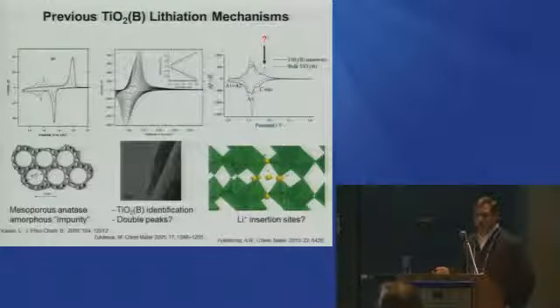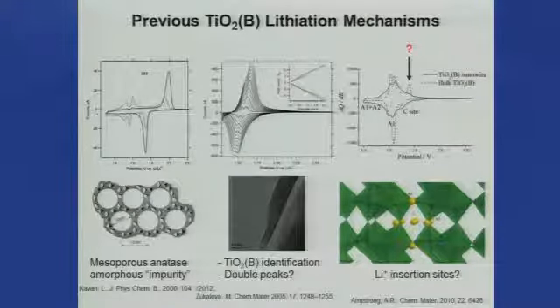Okay, we went back to the literature to try to understand this, and we found, of course, these papers. We actually knew about these papers before we even made TiO2B, where early on Grätzel reported that you'd get these surface phases in anatase, which he was trying to template into this mesoporous network, and he thought that these were just amorphous TiO2 phases with anatase crystals embedded in them. And so people started to investigate this as they started to make different nanowires and nanorods. But really the short end of the story is the merging of theory, where they did calculations and compared it to phase impure materials to try to understand which sites fill first.